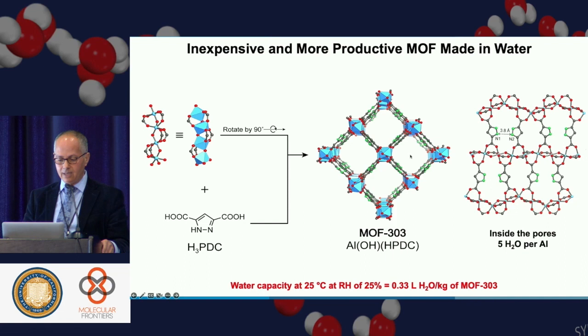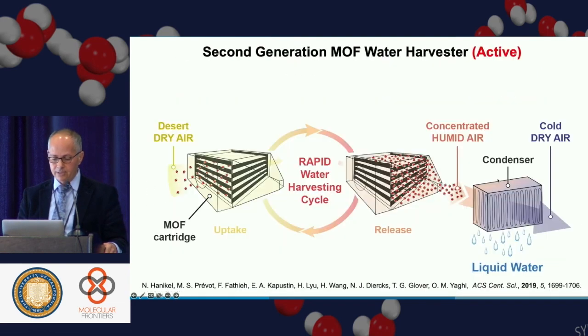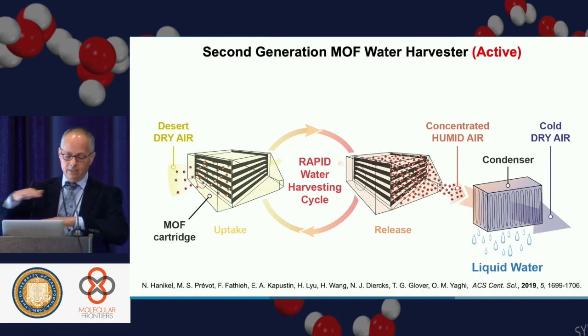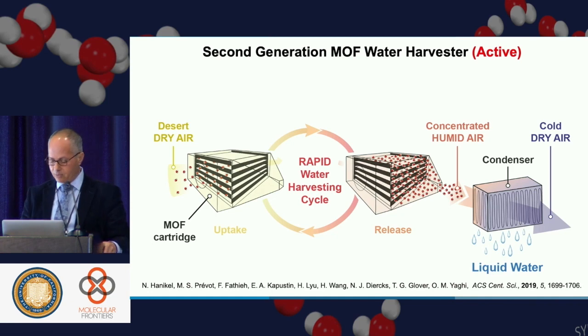And if your eye is inside the pore, you'll see this. You'll see the hydrophilic pocket and a hydrophobic pocket. This is the NH on this side, NH on that side. Perfect for water seeding. Water goes in here, and it has a hydrogen bond donor and acceptor. So hydrophilic, hydrophobic, hydrophilic, hydrophilic, hydrophobic, they alternate throughout the material, and that's a material that we designed, a different prototype now with basically layers of MOF to expose more of the MOF and